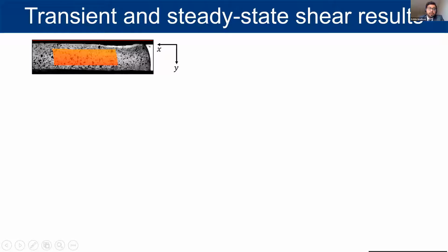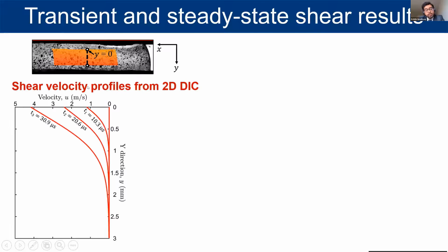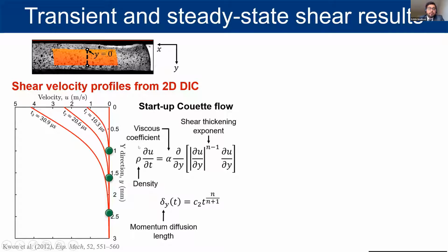In the transient state of deformation, the shear momentum is traveling from the top to the bottom plate. Kwon et al. from our research group showed that the only quantity of interest in this stage is the velocity field across any line segment drawn across the width of the sample. And this is exactly what we get from DIC. These are the shear velocity profiles of any arbitrary line segment at different instances of time. From this velocity field, we also get the momentum diffusion length, which is the length up to which the momentum has diffused at any given time. From these two quantities, the velocity and the momentum diffusion length, we can finally solve the constitutive model, which is the Navier-Stokes equation of startup fluid flow, and obtain the two model parameters of viscous coefficient and the shear thickening exponent. For PDMS, I obtained these values.